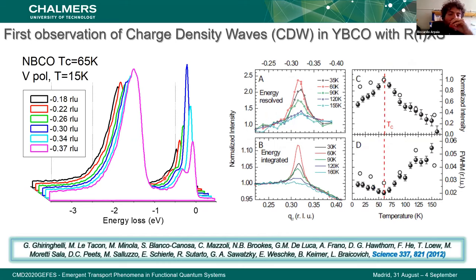As I mentioned a few minutes ago, the first observation of incommensurate charge density wave was in YBCO and was done by using RIXS. Here we see different spectra at different momenta along the H direction, in reciprocal lattice units. As you can see, the intensity of the quasi-elastic region, close to zero energy loss, changes as a function of momentum, with a maximum reached at a Q vector of 0.30. The intensity of this quasi-elastic region is integrated and plotted here as a function of temperature. The competition with superconductivity is highlighted by the fact that the intensity of this charge order peak increases when approaching Tc, but then below Tc starts being suppressed.